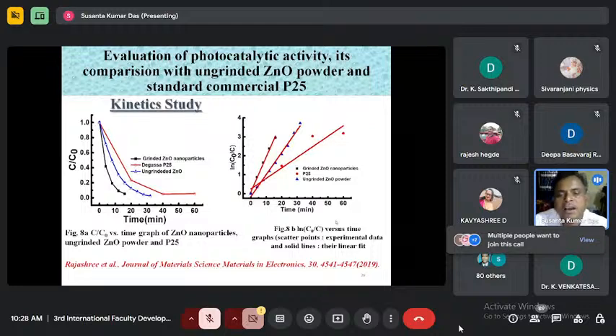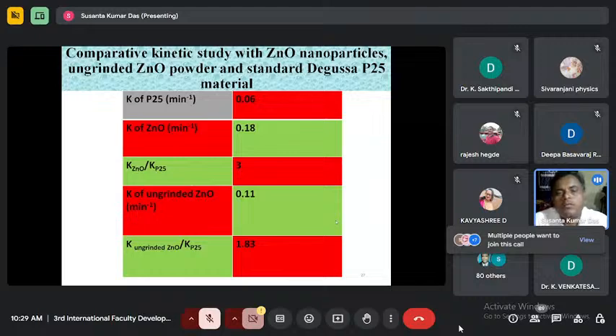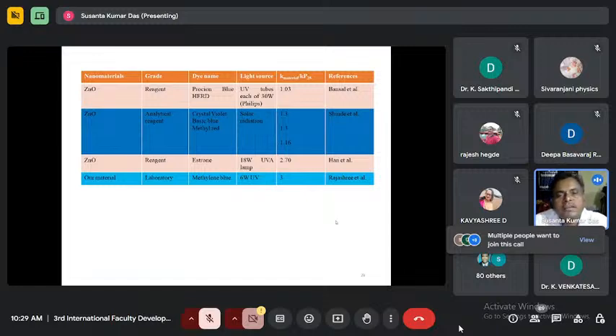So the slope is very high for our materials. You can see in comparison to the Degussa P25, which is the standard material. From that slope, we found that for P25 it is coming 0.06, whereas for our material it is coming 0.18. That means around 3 times enhancement of the reaction rate constant was found, whereas in ungrounded it was found to be a little bit less. Then we tried comparing how much other people have shown in the world. Then we found that ours is the highest in this, so it is really showing good results at that time.